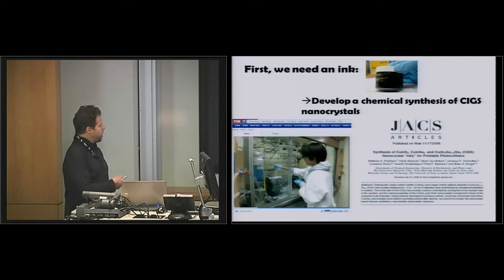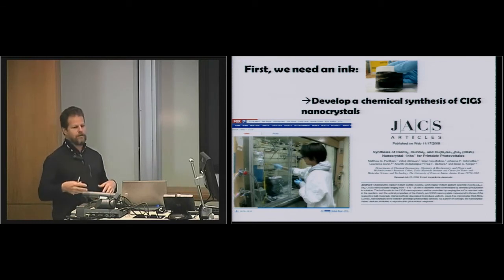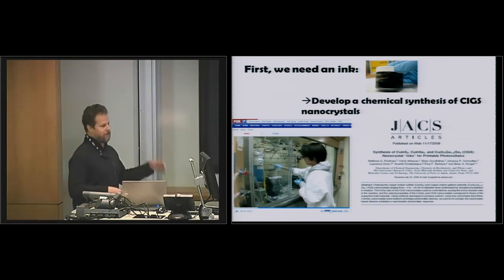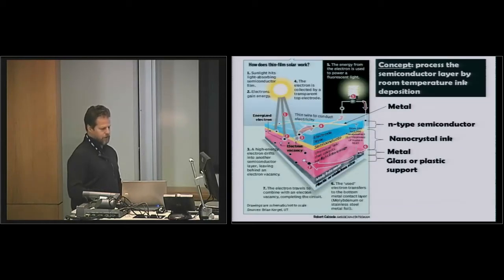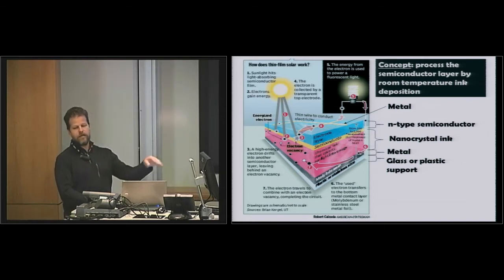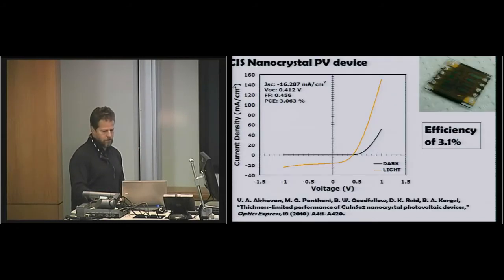And so this is one undergrad that was working in my group, Daria Reed, and she happened to be in the lab working when the television crew came in, so she got to be on TV making some nanocrystals, and a couple of undergrads doing some work at that time. So the CIGS device is glass with a metal back contact. This ink is what we're trying to deposit, and then a top layer. If you want to paint an entire device, you need to have inks or paints for all of these layers. And so we haven't gotten to that point. We just paint on our absorber layer and then vapor deposit zinc oxide and ITO on the top.